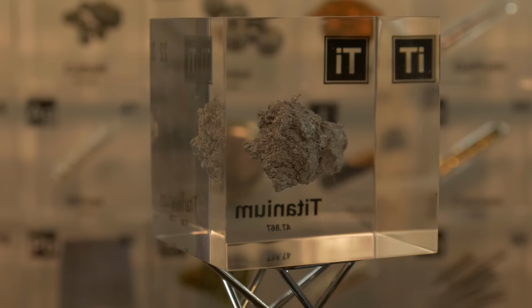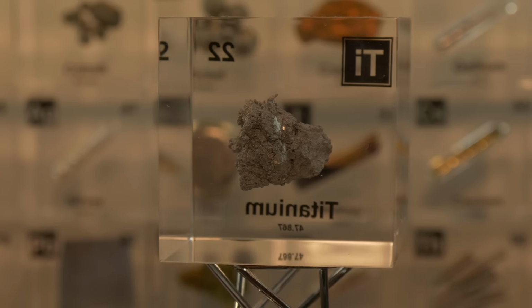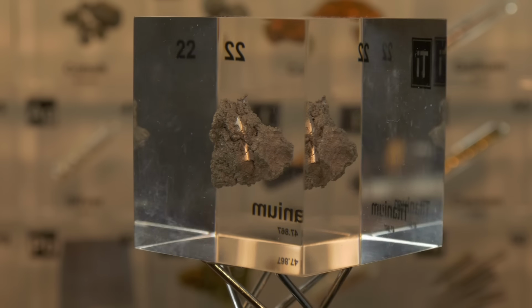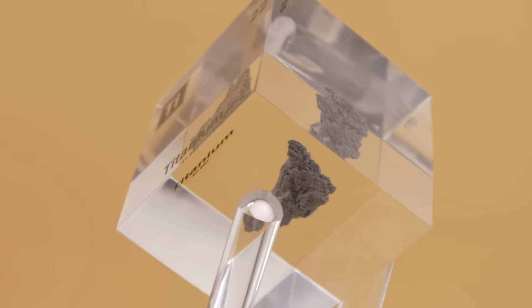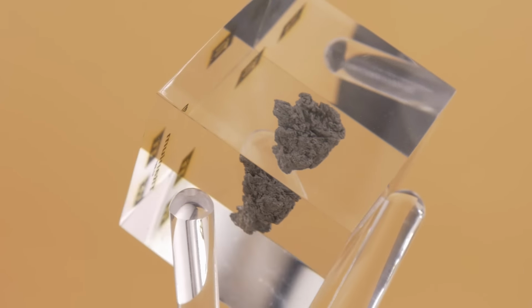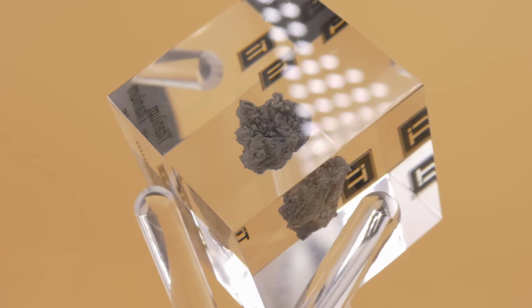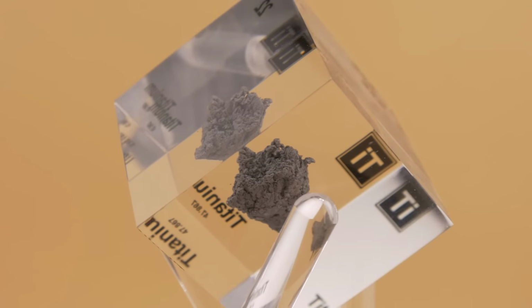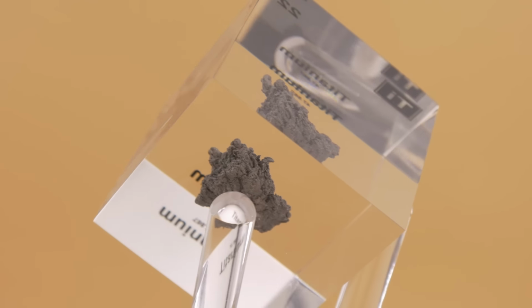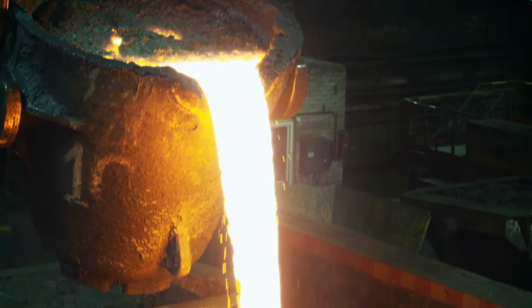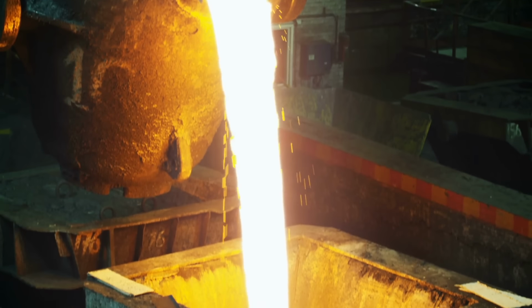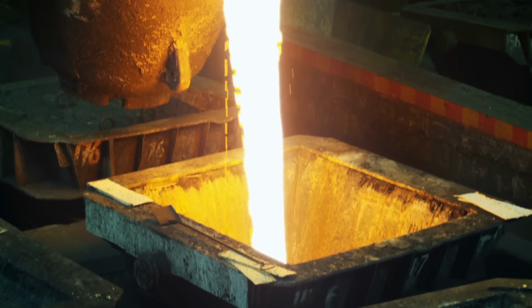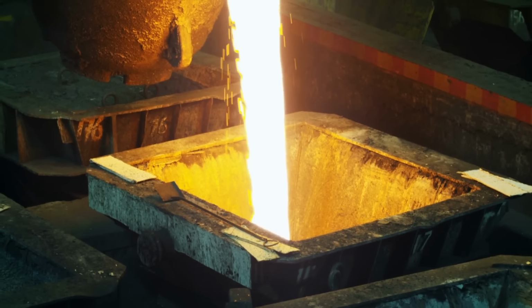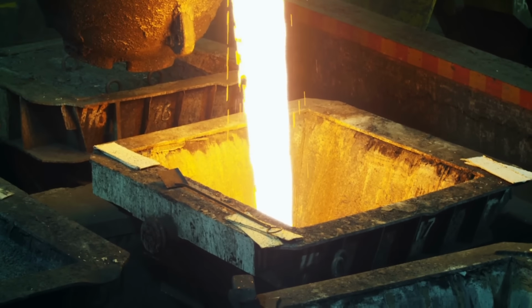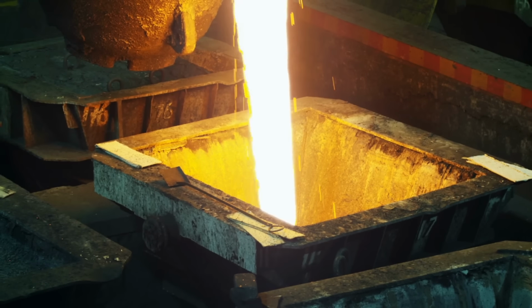But titanium also has a strong appetite for oxygen. Even a little oxygen picked up in the metal can make it less flexible and more brittle. So, working with titanium, casting, forging, etc., often requires very careful control of the atmosphere and impurities. Titanium has a high melting point of about 1668 degrees Celsius or 3034 degrees Fahrenheit. That is much higher than aluminum at 660 degrees Celsius, and a bit higher than steel.